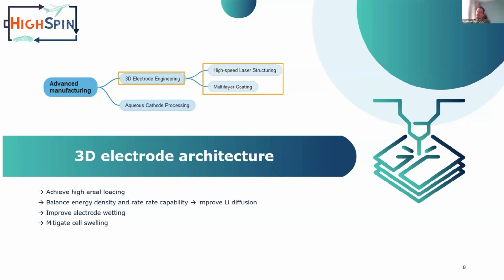Then going on to the 3D electrode architecture side, I think this is a quite interesting aspect of the project. This is comprised of two components: multi-layer coating and high-speed laser structuring. The objective here is to square the circle, if you will, between a few different things that are often trade-offs. We want to achieve high areal loading on the electrodes to obtain high energy density. But of course, that often comes at the trade-off of reduced rate capability. And so we want to try to balance these two things.